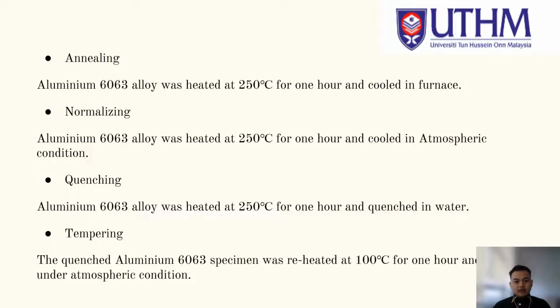For this slide, I will tell all of you about the heat treatment process carried out in this research paper. For the first, is annealing. Annealing is the process of heating the metals near its recrystallization temperature and cooling at very low thermal rate. In this paper, aluminium 6063 alloy was heated at 250 degrees Celsius for 1 hour and cooled in furnace.